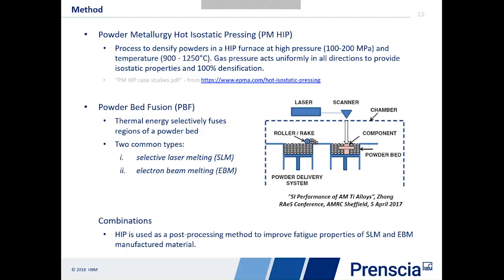Now, in addition to those, we can do post-heat treatments as well. We can create an additive manufactured component using powder bed fusion, and then we can heat treat it by hipping afterwards. This has the effect of homogenizing the properties somewhat, so they become far more consistent, and in our case, potentially better in fatigue. So we're also looking at different combinations of hipped or unhipped processes.